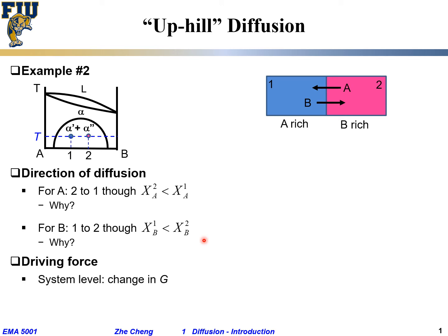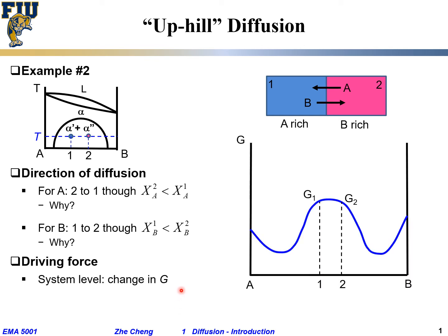To understand why, we go back to thermodynamics. The driving force for system change is always due to the change in system Gibbs free energy. For temperatures below the miscibility gap, the Gibbs free energy versus composition curve has an interesting shape: higher in the middle, then lower, then higher again toward the ends — a characteristic double-well shape. For piece one it corresponds to G1, which represents the initial molar Gibbs free energy for piece one; G2 represents the molar Gibbs free energy for piece two.